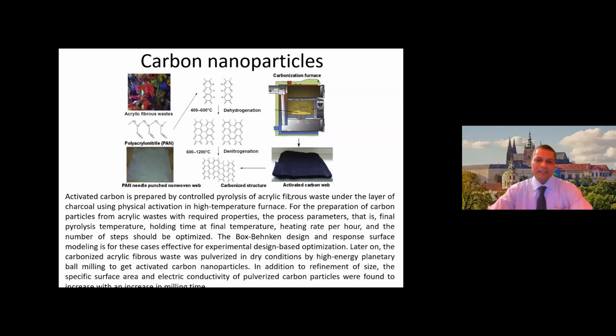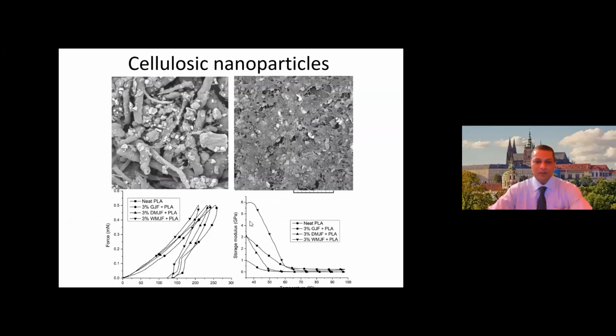Especially the nanoparticles of carbon are created from waste materials of textile, acrylic-based textile, because by pyrolysis of acrylic we are able to create nanofibers and nanoparticles. It is also possible to have nanoparticles from cellulose, waste cellulose fiber, for that matter jute or any other fiber from plants, which can be alkali treated to remove the lignin and other unwanted hemicellulose material. Then the pure crystalline cellulose remains, because by this treatment the amorphous parts are removed, or the macrostructure is broken into microcrystalline structures, and further by mechanical action like cryogenic ball milling, it is possible to have nanofibrils or